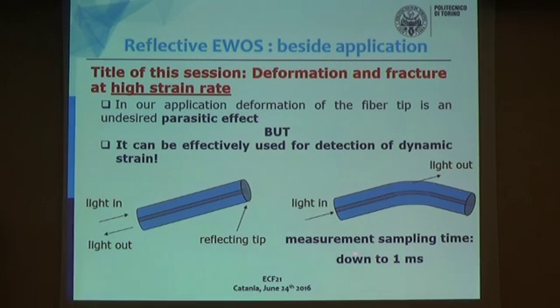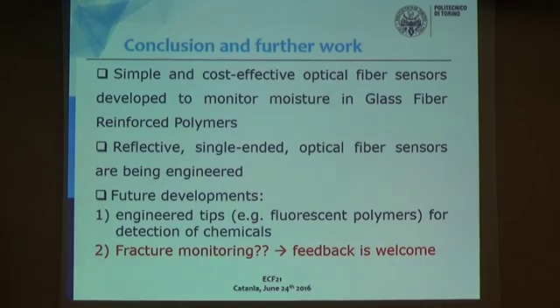And what is the frequency that we can sample? This is basically constrained by the equipment you are using. In our case, we can easily perform measurements at 1 kilohertz or even above. Okay, so the conclusion: we produced simple and cost-effective optical fiber sensors for measuring diffusion of water into polymer for oil applications. We developed these single-ended reflective sensors that are easy to embed into the polymer matrix.